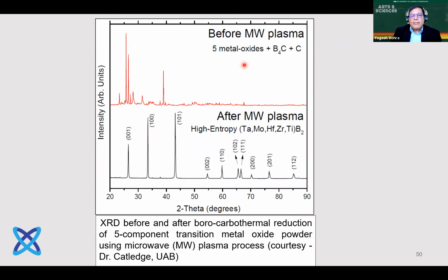what you do here is start with metal oxide as precursors, whatever metals you want in this plasma chemistry. So you start with the metal oxide, you mix them with a source of boron. Remember, our goal is to make borides, and then you have some additional carbon because it's a boro-carbothermal reduction using the low temperature plasma. So you start with oxide, which has a very complex pattern in X-ray diffraction.